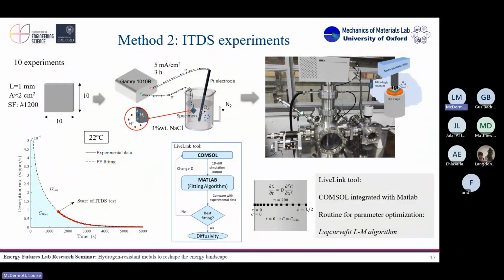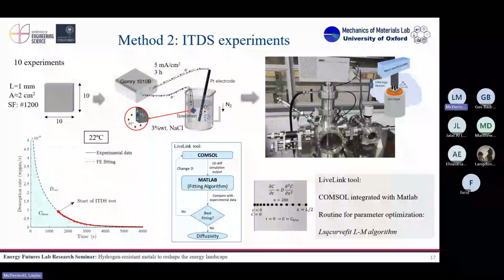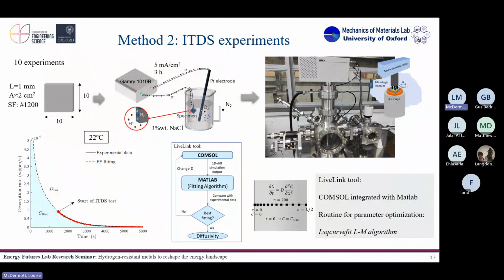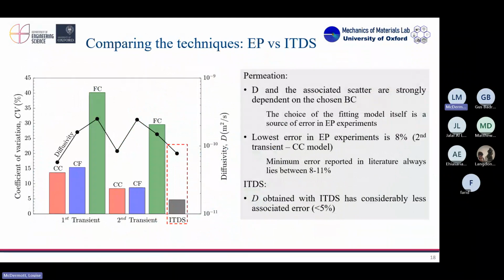The sample is initially saturated with hydrogen, completely filled with hydrogen. You leave it desorbing in the TDS, and you record the desorption rate versus time. In the end, you get a curve like this that you can also fit to Fick's second law, and you can obtain the diffusivity. The only thing you need to fit is the diffusivity. So we adopted these two experimental approaches, permeation and desorption in the TDS, and we compared the results.